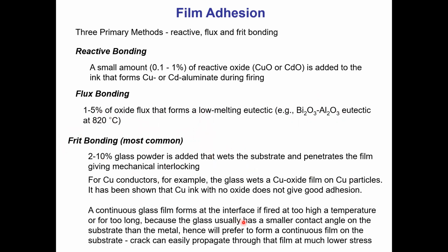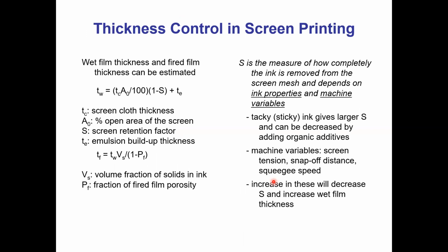And finally, the frit bonding is the most popular one that is used in the industry. So you add, again, small fraction of a glass frit, and at the softening temperature heat treatment, the glass will soften. That softened glass will get into the surface rough area of the substrate and make a mechanical interlocking, and that way you can get bonding. So these are the three different types of bonding that one uses, but the industry uses primarily the glass frit bonding.